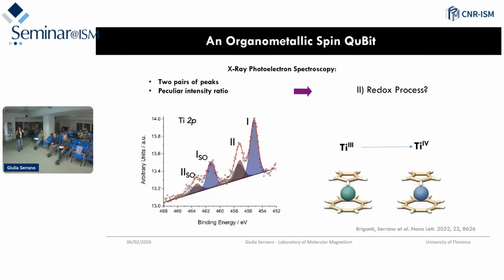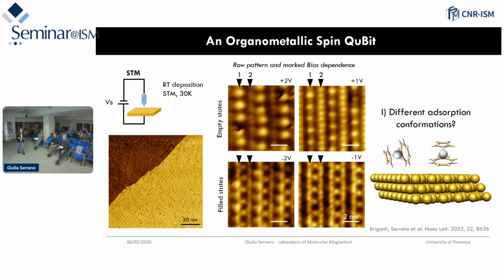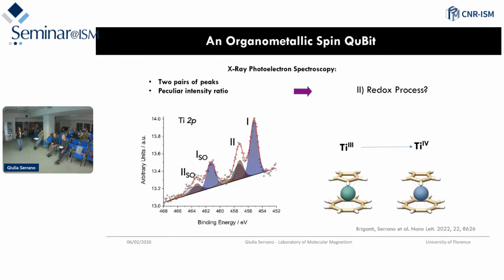This is the point. What we saw at the beginning was really a puzzling work for us. It took some time to understand the picture. So we saw this bias dependence. It was quite strange actually, and we saw by the XPS that we had the titanium 3 plus contribution that we expected, and a titanium 4 plus contribution. The titanium 3 plus also has its satellite peak, but it was not enough to explain the height of this second peak. So we knew that on the surface we had titanium 3 plus and some titanium 4 plus species. This is something that we knew by the XPS. It's a nice skill because many STM people do just STM and cannot access the oxidation state, the average oxidation state. So this is, I would say, important information.